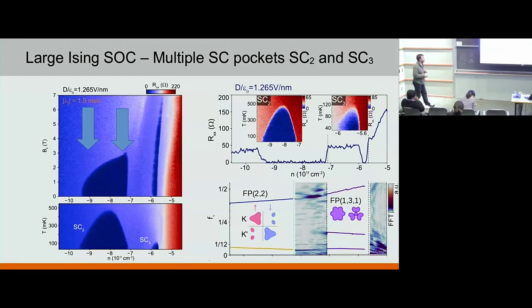Okay. So now, if you look far away, so this portion of the phase here, and far away into the normal state, it's relatively simple to convince yourself that this is the 2-4 phase, which is exactly the same as we found in the previous samples with large spin orbit coupling. So in contrast to the small spin orbit coupling sample, where you have 2 big, 2 small surfaces, now you have 2 big and 4 small surfaces, okay? And we are just assuming that there's no intervalley coherence, but the idea is that you have some kind of spin valley arrangement like this, okay?